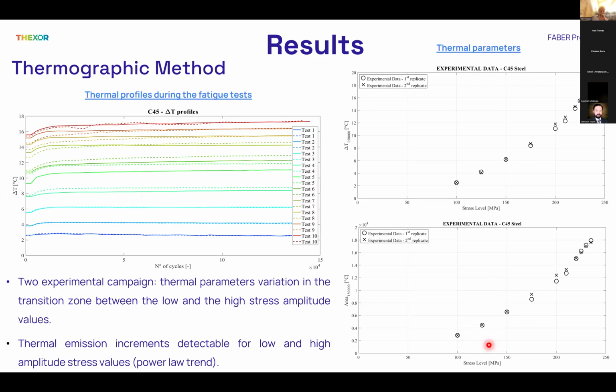The thermal emissions prior to the fatigue limit analysis using the thermographic method is reported in this slide. The thermographic activity was carried out with two experimental campaigns in order to provide multiple results for this research activity.